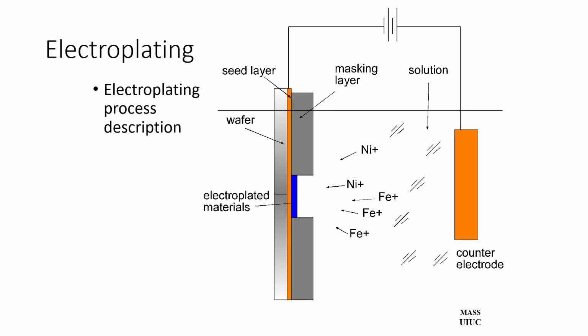Another type of processing is called electroplating. In electroplating, you put a wafer with a mold. The mold is typically a mask resist layer into a plating bath. There is a layer of seed metal, seed layer, that is connected to the electrodes. And for example, you can have a source counter electrode on the other side. And once the electric current is on, it will pull materials off this source and deposit it into the gaps in between the photoresist. And then you can remove the photoresist.